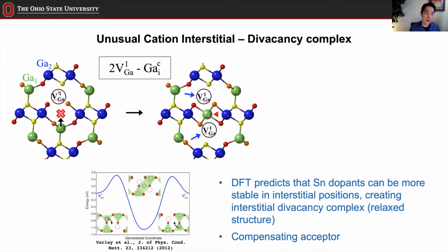Okay, so if there is a vacancy, which can form naturally in any material, but in this material, if the vacancy is formed at the tetrahedral gallium-1 site, then that configuration is in fact not energetically stable. So it has a high energy state. So whenever you have this vacancy, the system doesn't want this anymore. Therefore, what is likely going to happen is the neighboring gallium-1 site atom, another tetrahedral atom, can jump into the interstitial site. Okay, so then what happens?